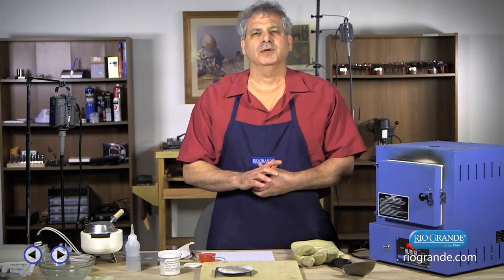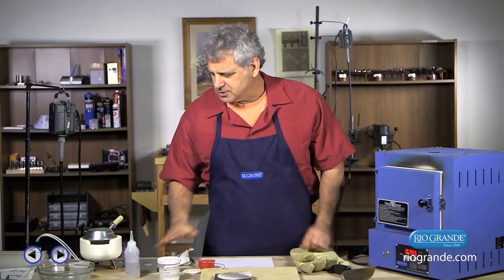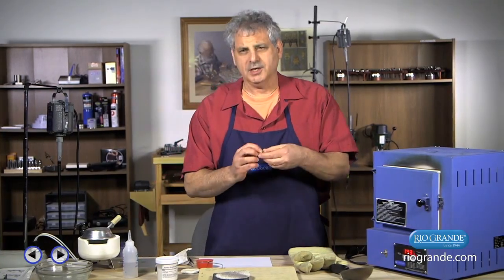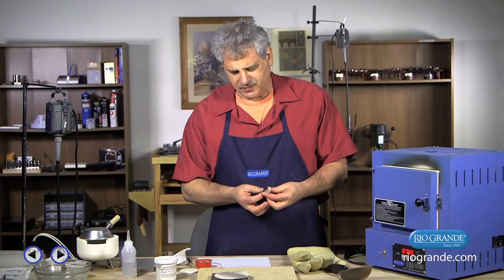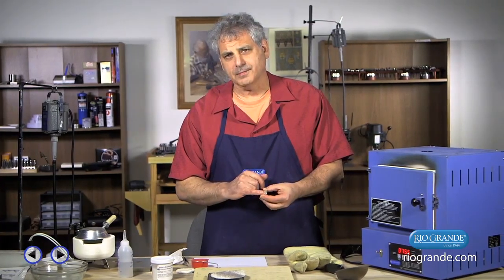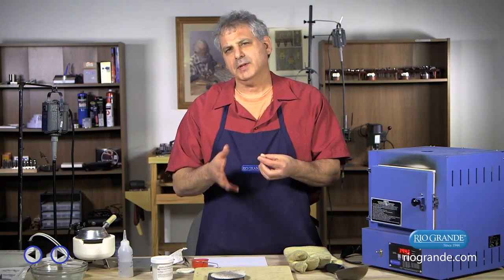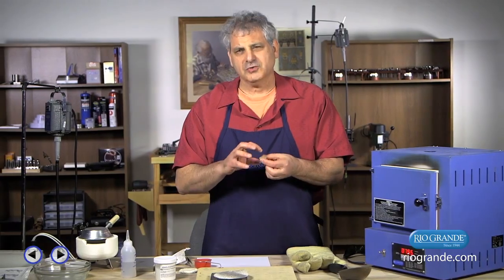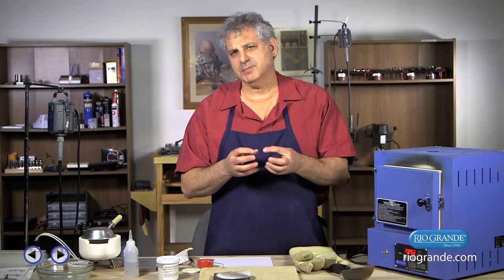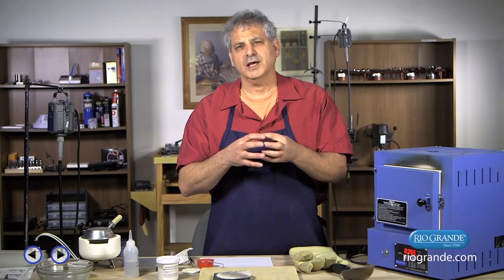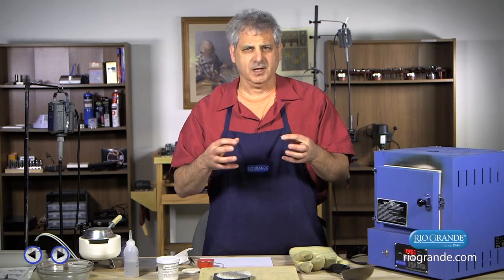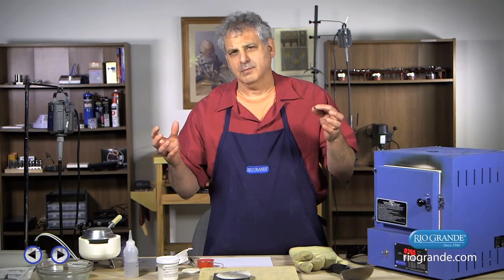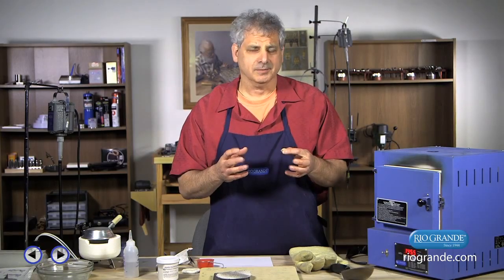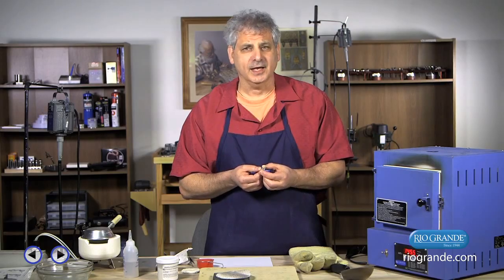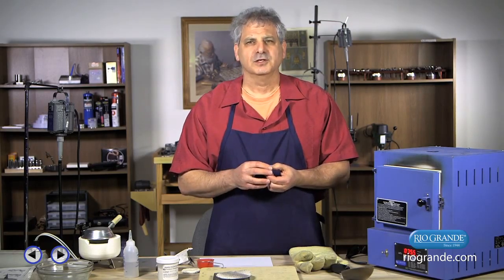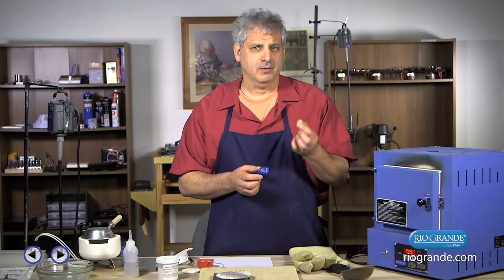And the next step is going to be something called counter enamel. So right now, I've got a nice dome, I've got a nice metallic surface, I've got a layer of clear enamel on here, and what's going to happen, the more enamel I put on the front here, the more stress is going to happen on this piece, because when I'm heating this piece up, the metal's going to heat, the glass is going to melt and expand just like the metal's expanding. When the piece cools, the metal starts to shrink, but the glass doesn't want to shrink. And there's a stress, and the glass is more likely to crack than the metal, so I start to get cracks. So a very thin layer on a piece of metal will be fine.